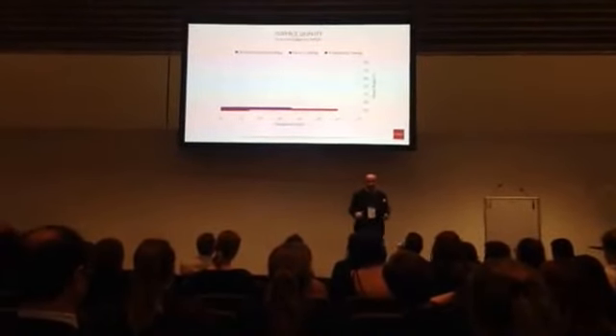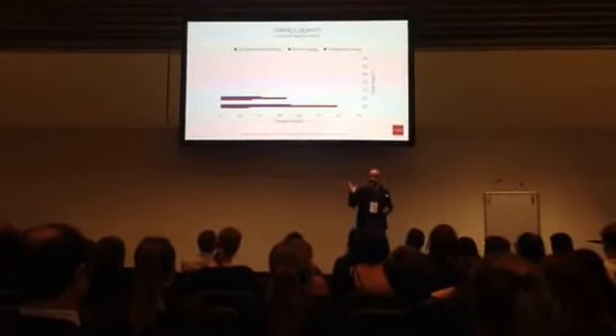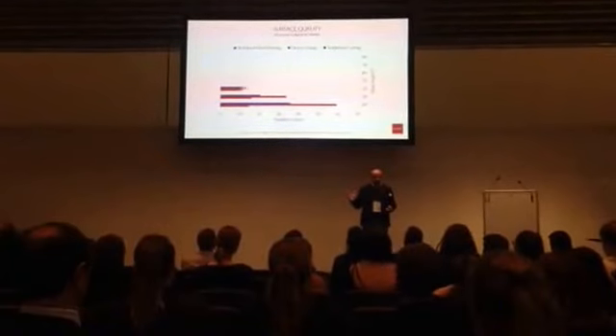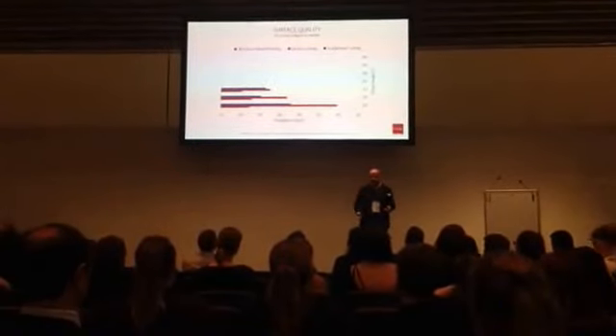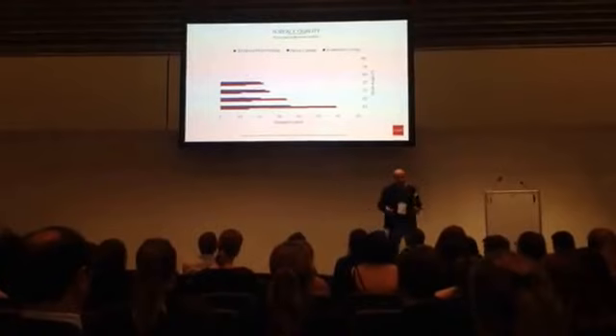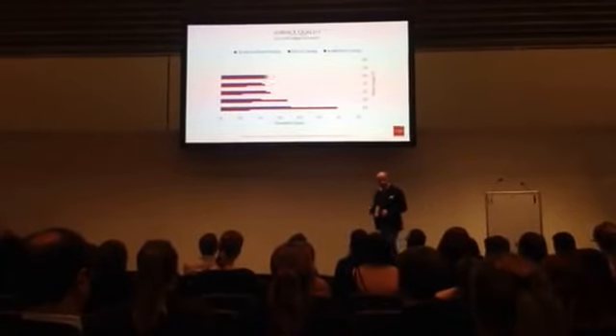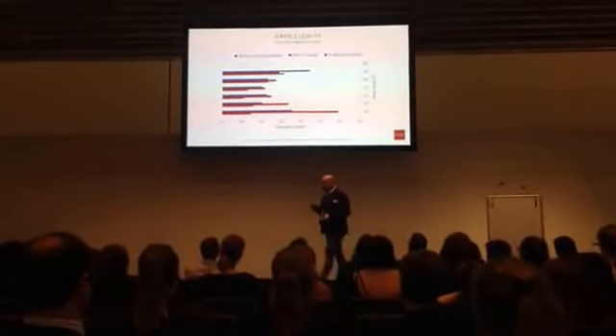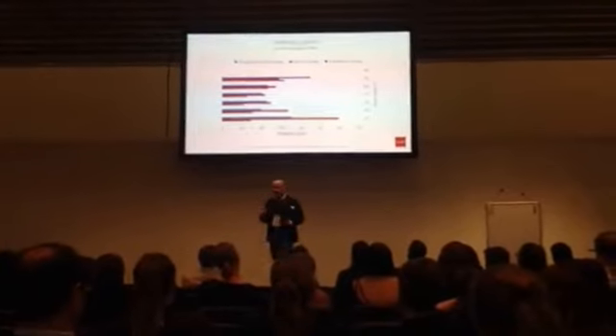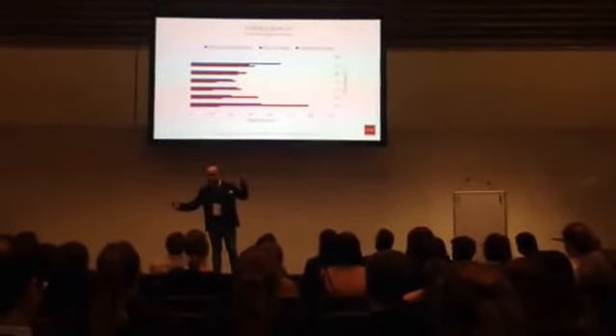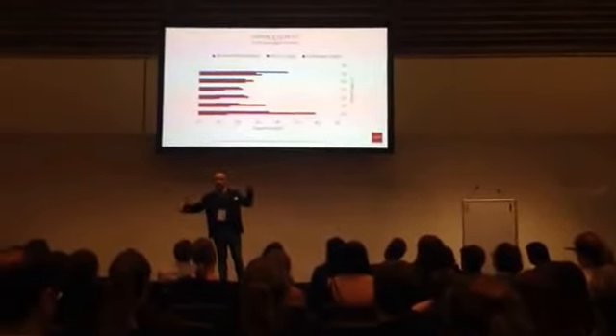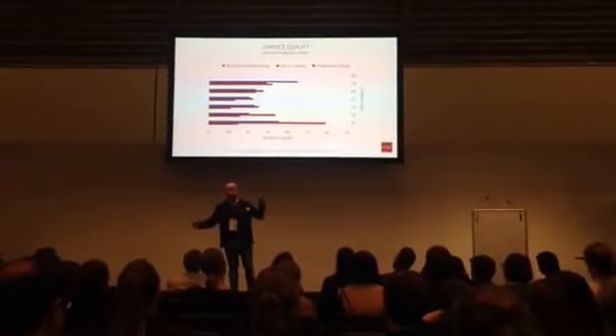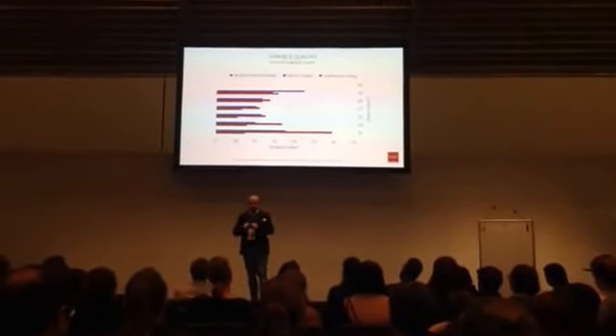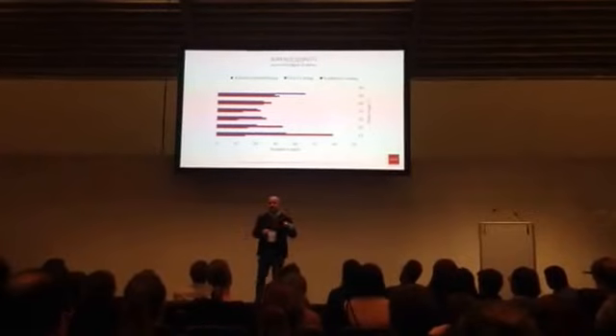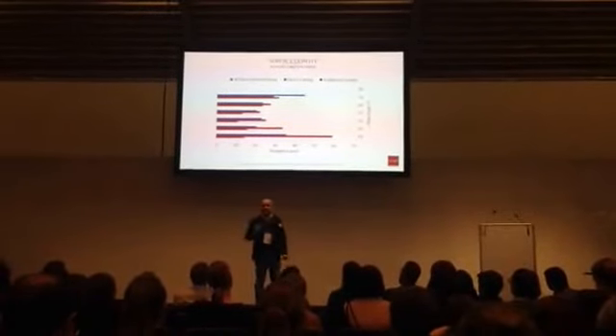And direct casting is around 35. But when you increase the angle, then 3D printing starts to get an advantage. So I will say that talking about the roughness, there is no story between 3D printing and traditional casting, because traditional casting is always much more smooth. But if we compare with direct casting, I will say that it's similar.